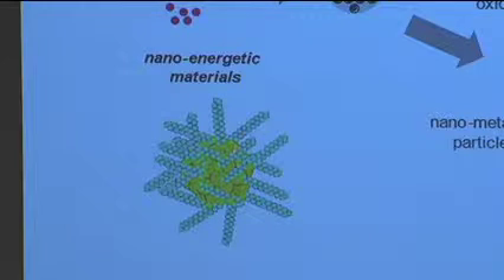Now, the hydrocarbon ligand here is essentially my binder. Remember I told you in the solid propellant I have a fuel, a binder, and an oxidizer? Well, suppose I want to make this into a nanocomposite energetic material. Well, okay, now I've got my fuel here in the center. I've got my binder coming out here that's covering the fuel. Suppose now I come back and I say I want to functionalize the tail end of this ligand. And I want to put some oxidizer on that surface, maybe in the form of nitrogen dioxide groups, fluorine groups, or whatever. And so all of a sudden, at the nanometer scale, I'll have my fuel, my binder, and my oxidizer. Okay? So I have a nanocomposite that could be essentially controlled in terms of its ignition characteristics and the reactivity depending on the size and the structure of this.